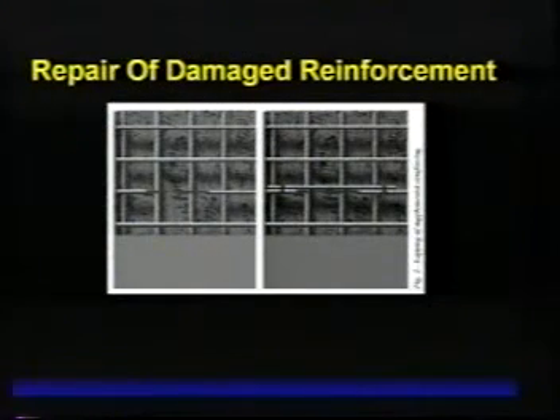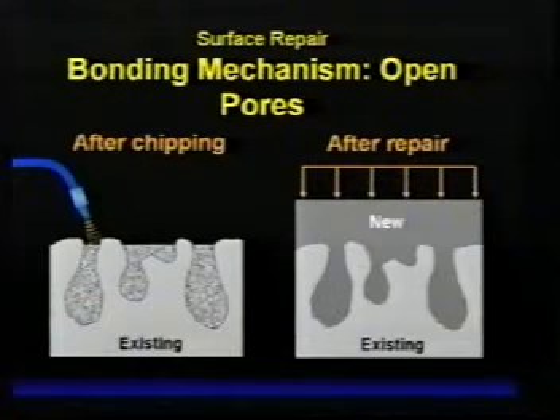If the bars are damaged, it's very important that the bars be looked at by a structural engineer and a repair method determined, whether it's splicing or other techniques to repair the damaged reinforcing steel. The next step is in preparation to make sure that we have a surface that will accept the new repair material, and that's one of the purposes of the water cleaning and also the abrasive blasting, is to remove any of the materials that might be on the surface that would inhibit the bond and the absorption of the new material into the substrate.